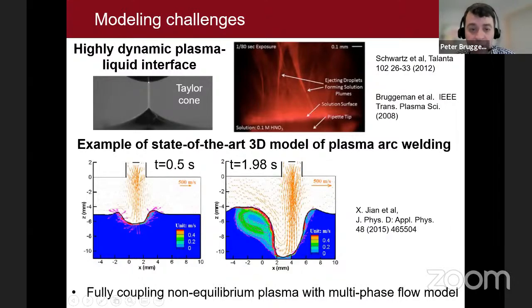This has been reasonably done. The reason there is that the plasma model is, of course, much easier because you can assume almost equilibrium, and in these models this is done. And then you can model what the plasma is doing, how the molten metal and the evaporation of the metal in the plasma is impacting the welding process. And there predictability has occurred and has been able to, for example, improve welding processes. But in the conditions where I'm talking, the models are less developed because we have these non-equilibrium effects that are just way more difficult to incorporate in the models.